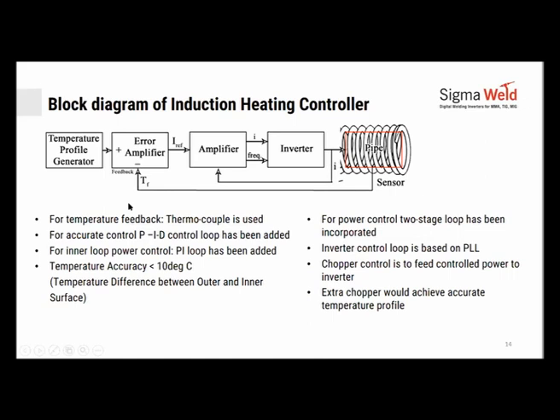You can have a temperature feedback system. You can also work in open loop. An accurate PID control loop has been added, which gives you much better control on the temperature profile. For inner loop power control, a PI loop has been added. So accuracies are under 10 degrees in the temperature difference between the outer and inner surface.